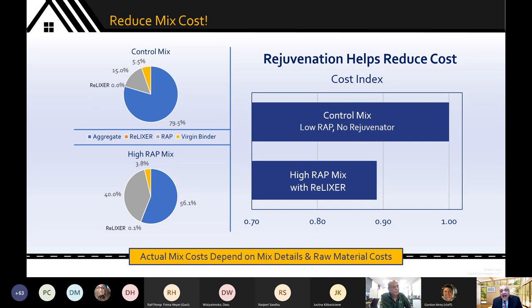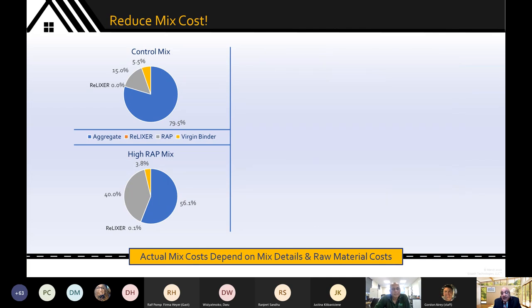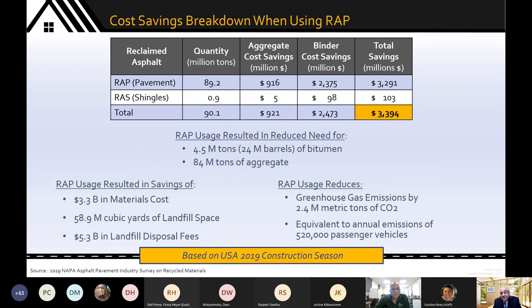But in general, as the previous data showed, as you force more and more of your wrapped bitumen to start behaving like virgin bitumen through rejuvenation, you're able to cut down on virgin material use. Not only are you cutting down on mining of aggregate, but you're also cutting down on virgin bitumen. And that is what leads to this cost reduction, anywhere from 5 to 15%, depending on your experiences, depending on your level of wrap addition, depending on your assumptions about input raw material costs. This is the underpinning that leads to the previous chart.